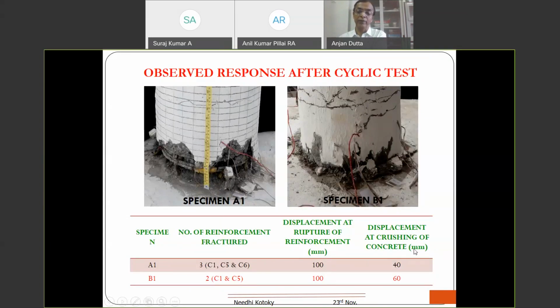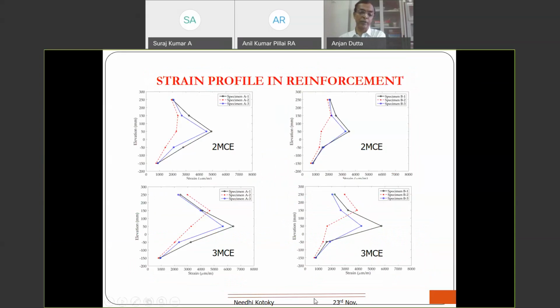displacement level, 100 millimeter. And you can see the concrete crushing was happening at 40 millimeter for the specimen without fiber, and the same thing was happening at 60 millimeter with fiber. Only two reinforcement got ruptured eventually for the specimen with fiber, whereas one more additional reinforcement got ruptured in the specimen without fiber. And you can also see that for the specimen without fiber, the strain is close to 6,000, and this is close to 6,000.